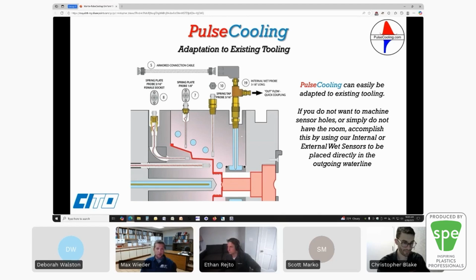If you do not want to impede your flow line, your water line, we have an external sensor that is placed up here in the fitting itself. Because the sensor is not in the mold steel or near the molding surface itself, we use a pulse advance program to advance our cooling media, so we can set when we want the media to advance and for how long to stay on to get the cooling where it needs to be in that tool.